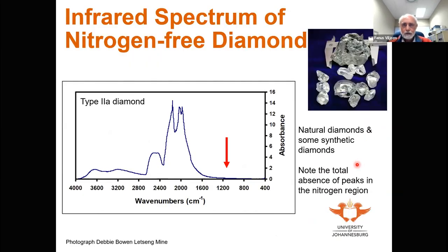This is an example of a nitrogen-free diamond. As you can see here, there are no nitrogen peaks present. We classify these diamonds as type 2A diamonds. And that's an example of what these stones look like. For example, these are nitrogen-free diamonds from the Letseng diamond mine in Lesotho. We also encounter these diamonds from the Karowe mine in Botswana, and that's a very typical nitrogen-free infrared spectrum. There are no nitrogen peaks present.